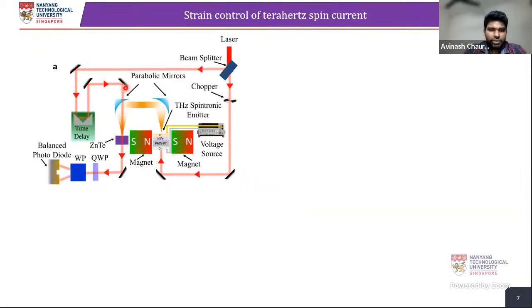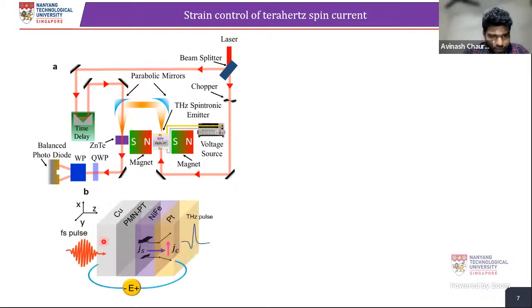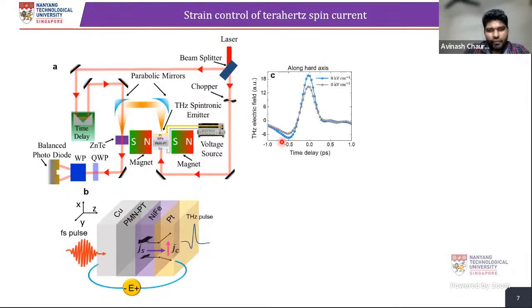So for that, we use the terahertz time domain spectroscopy measurement. So our device is here. If I zoom in, it will look like this. So we send the laser pulse and we apply the electric field across the thickness of the device. So what we do, suppose we do the measurement by applying 8 kilovolt, initially at 0. By applying 8, we can see the increase in the amplitude, which clearly indicates that with the applied electric field, there is an increase in the amplitude of the terahertz pulse.